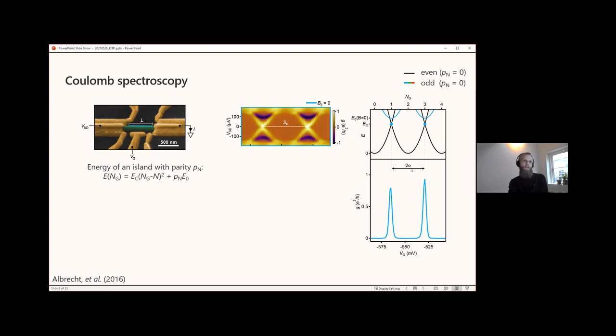Coming back to the parabolas, changing the gate voltage, or in this model the gate-induced charge offset, the island can be charged in units of two electrons, because in this case the charging energy is smaller than the superconducting gap, or the lowest energy state. And so the island is charged in portions of Cooper pairs. And then at the degeneracy points between these two even occupancy parabolas, we get a Coulomb blockade peak when we measure the conductance through the island.